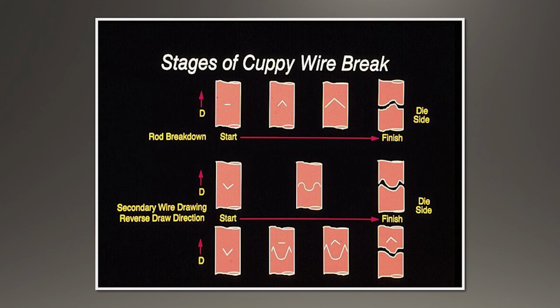Now here's a longitudinal cross-section of a wire. There's a wire break at the end, and you can see that there's some void that is present. But look now down over here. Here you can see a cone end pointing in the direction of wire drawing. But here now you can see the cone end pointing in the opposite direction. This is taking place in both directions, and it's not uncommon. So we have to be able to explain why this particular process takes place. So let's start over here schematically. Let's say in a rod breakdown machine, and something is wrong with the die, okay? Die angle, reduction in area, and a crack forms.